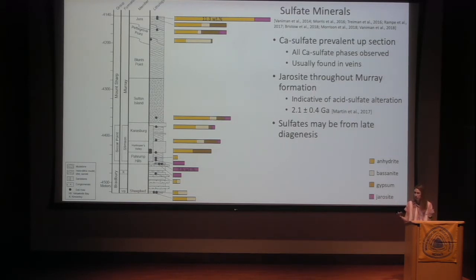Again, it's a ferric sulfate that forms from acid sulfate fluids at a pH of about 2 to 4. Another important finding about this jarosite in one of the samples from the Pahrump Hills is that the SAM instrument did potassium-argon age dating on it and got an age date of 2.1 billion years. This is an amazing discovery because remember, these sediments were deposited by lakes 3.5 billion years ago. And so this relatively young age for jarosite suggests that there was liquid water present on or in the subsurface of Gale crater over the course of maybe 1.5 billion years.